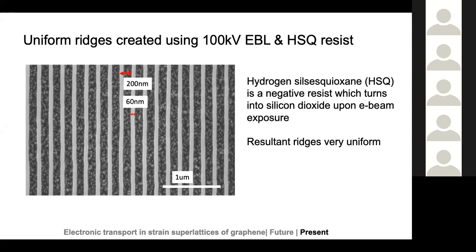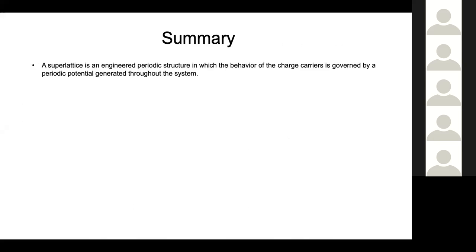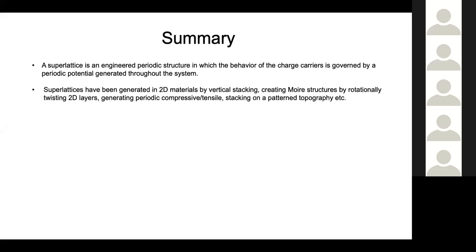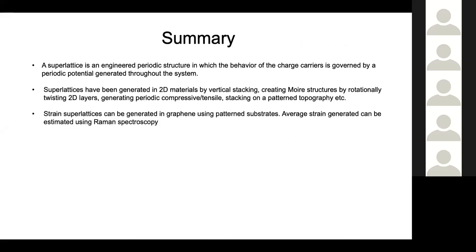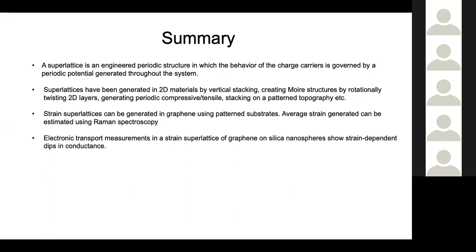And that will be exciting because we can see whether there's any resistance anisotropy showing up in the data or not. So in summary, we discussed what a superlattice is. We looked at some ways of generating superlattices in two-dimensional materials. In particular, we looked at strain superlattices in graphene, which were fabricated using a specific technique of patterned substrates. The average strain can be measured using Raman spectroscopy. Then we studied the electron transport in the systems, and what was observed is that there are additional dips in conductance which show up, which are strain dependent.